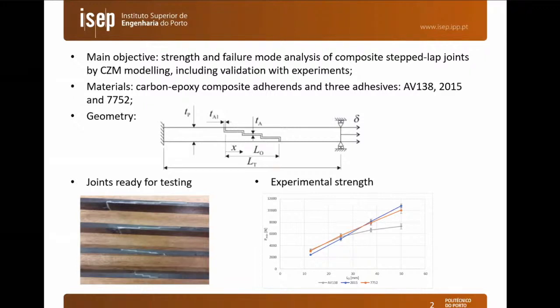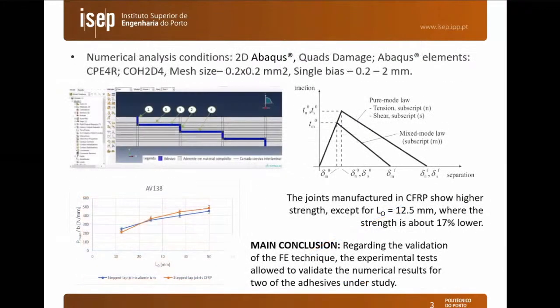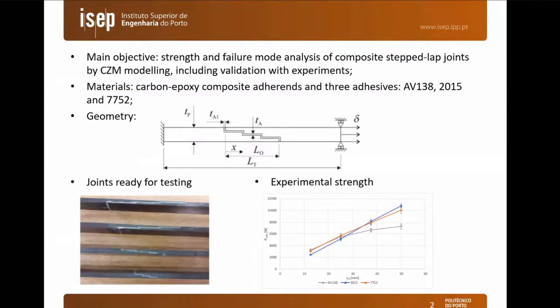We began by performing an experimental analysis of the joints, and in the graphic below to the right, we can see the failure strength of the joints for the three adhesives, with overlap lengths between 12.5 and 50 millimeters. We have a major difference between adhesives because of their ductility and their strength. For example, the AV138 behaves worse for high overlaps because it is very brittle, and it cannot account for the large peak stresses that develop in the adhesive.